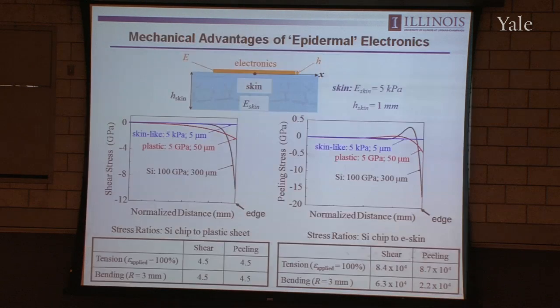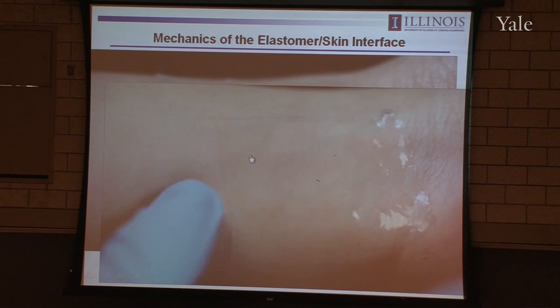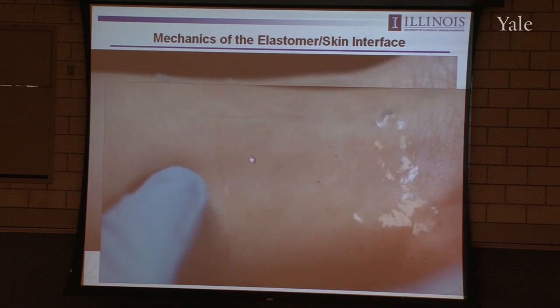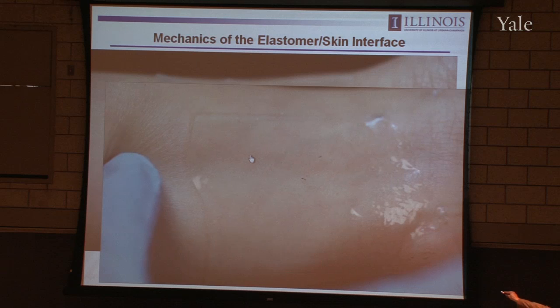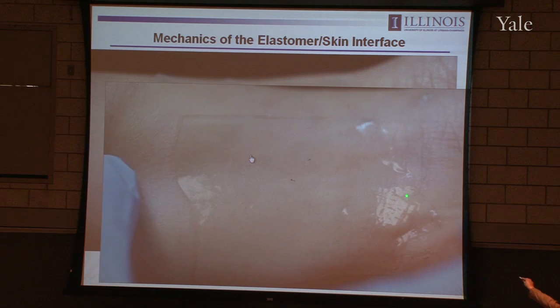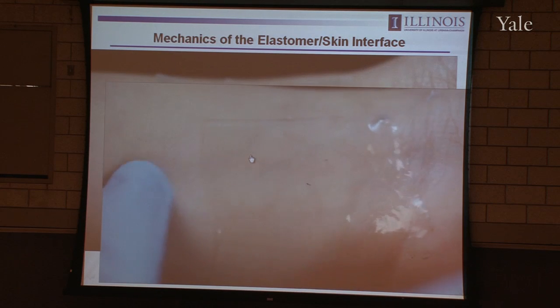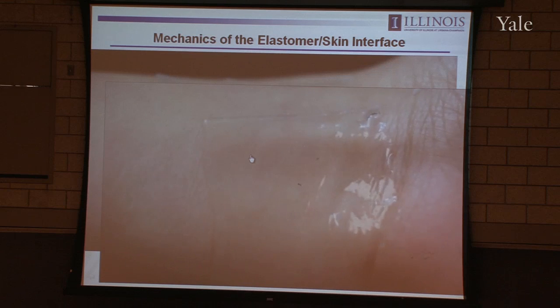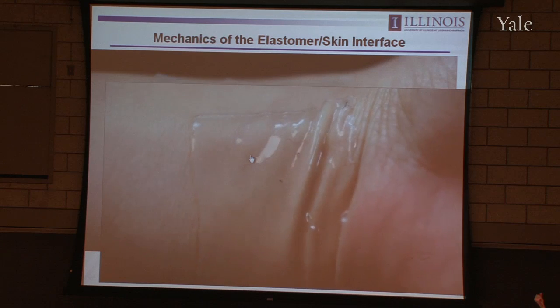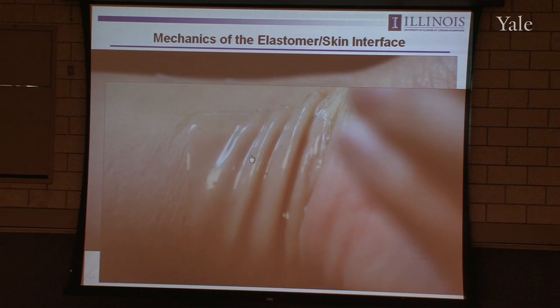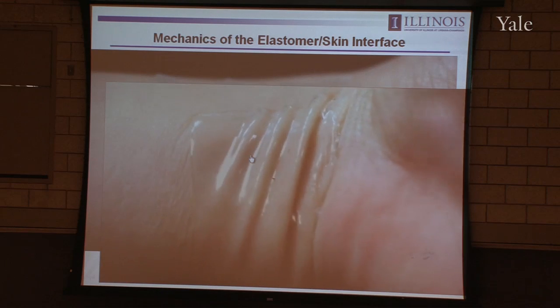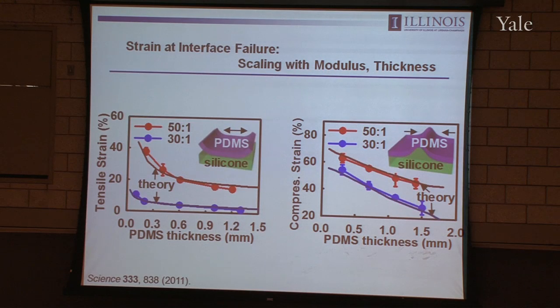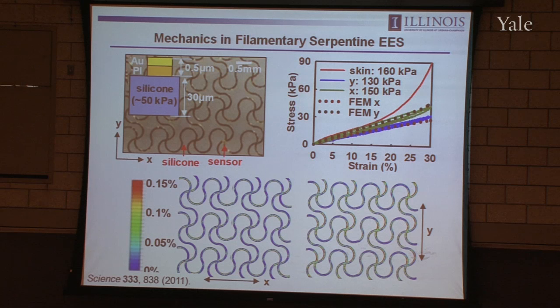If you do the same experiment, though, same material, just a slightly different formulation, so it's softer and thinner, then even without any adhesive at all, this is just laminated, just van der Waals forces against the skin, it's bonded very robustly. You stretch it as hard as you want. It doesn't come delaminated, and you can flex and move your wrist without causing the thing to peel off. And so it turns out you can look at that in a very quantitative way, and you can develop models for how that interface mechanics work, and I won't step you through that.